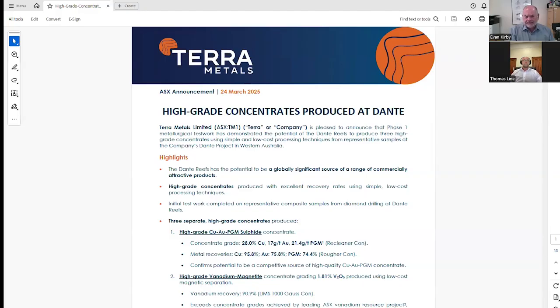The test work we undertook was structured to first recover the sulfides with associated copper and platinum group metals, and then recover a vanadium concentrate. The vanadium occurs in solid solution in magnetite, so effectively one is recovering a magnetite concentrate with vanadium contained in it, and then to look at the titanium.